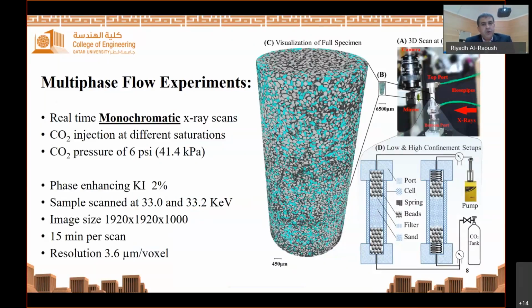In these experiments, CO2 was injected into saturated porous media and was imaged at different CO2 saturations. Monochromatic X-ray radiation was used to scan the specimen, and the injection of CO2 took place on the moving stage. As you can see here, the setup was equipped with top and bottom ports, which were linked to tubes that allowed fluid flow. The bottom port